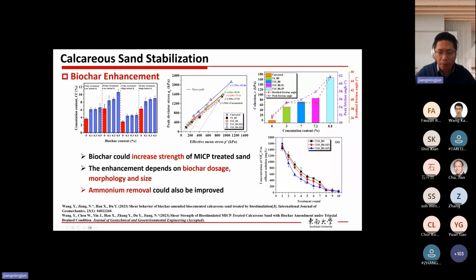So obviously, with the powder-shaped biochar, the concentration of ammonium decreases more quickly than the untreated one. So these results demonstrate that biochar, especially the powder-shaped biochar, could help to absorb some ammonium. In the future, maybe we could explore more to see how biochar could work effectively in field application to help reduce the ammonium problem.